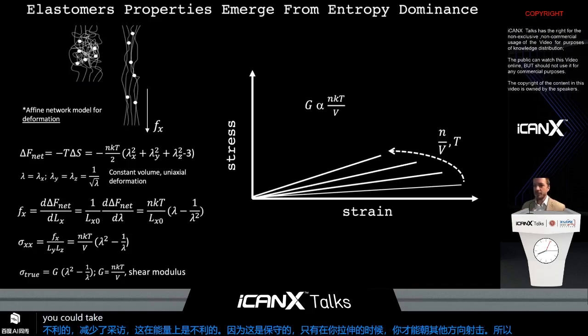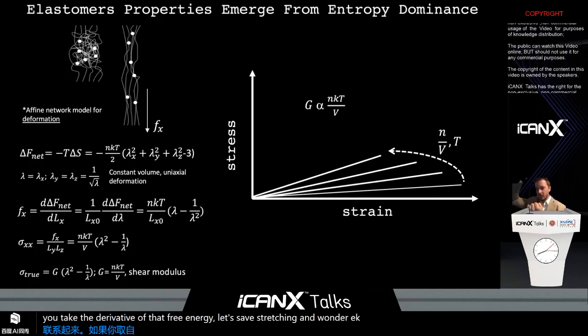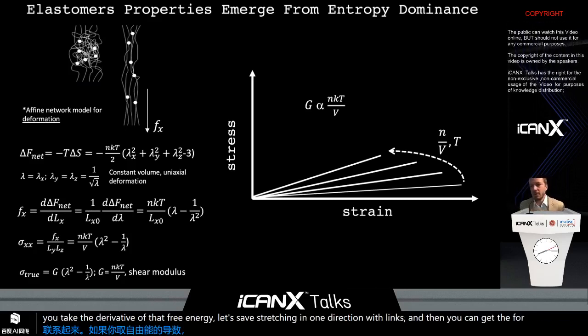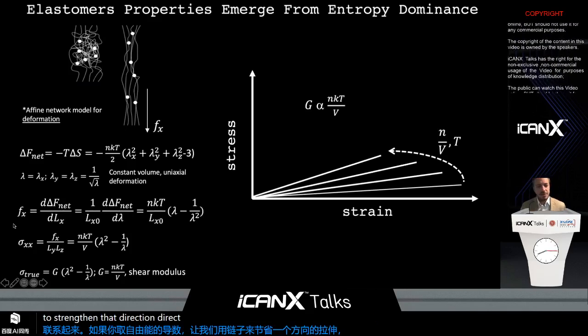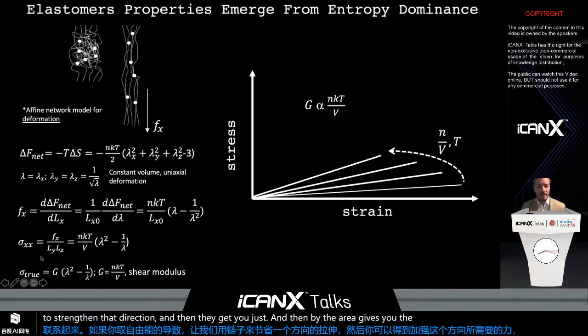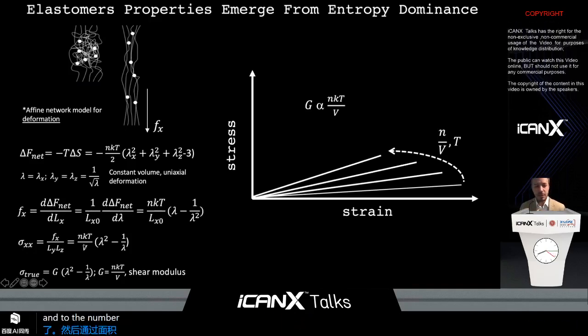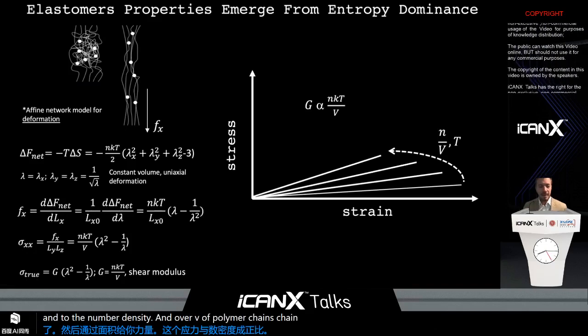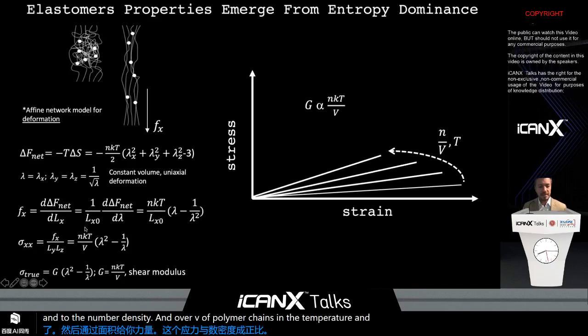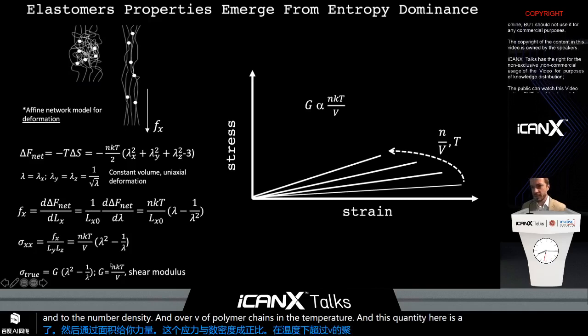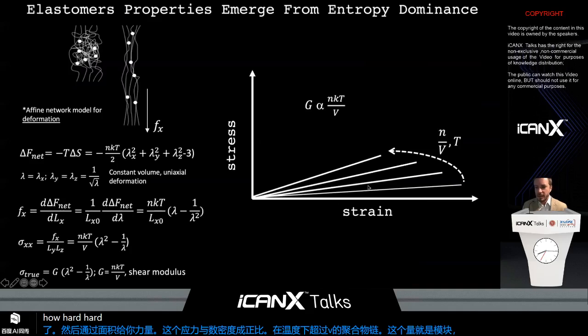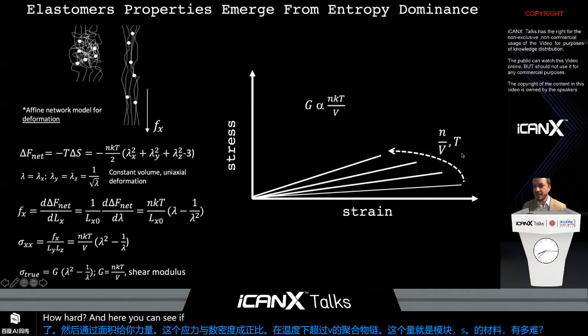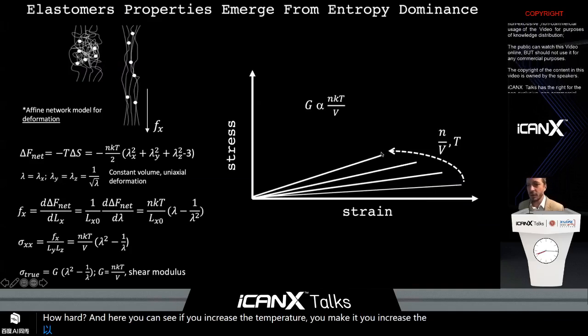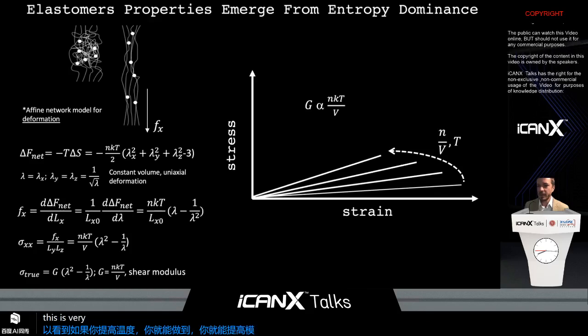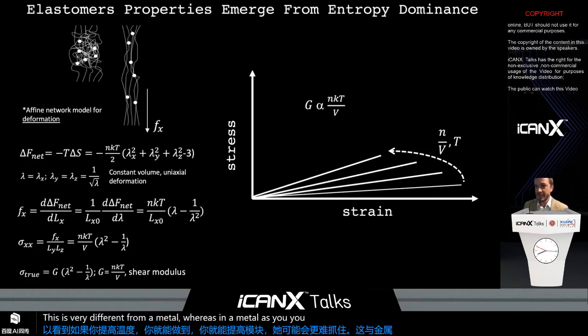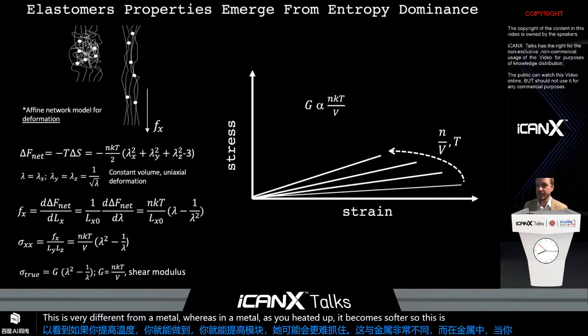And if you take the derivative of that free energy, let's say you're stretching in one direction with length, then you can get the force required to stretch in that direction. And then dividing by the area gives you the stress. And that stress is proportional to the number density, N over V, of polymer chains and the temperature. And this quantity here is the modulus of the material, how hard it is to stretch. And here you can see that if you increase the temperature, you increase the modulus, you make it harder to pull. And this is very different from a metal, whereas in a metal, as you heat it up, it becomes softer. So this is sort of like an alien material.